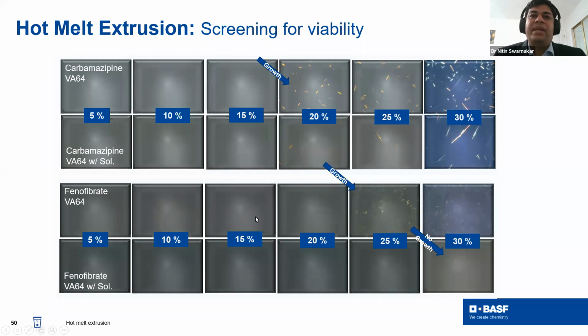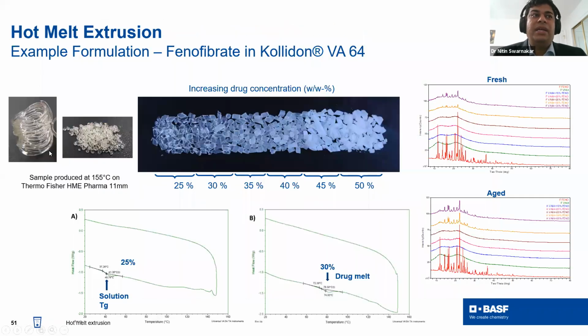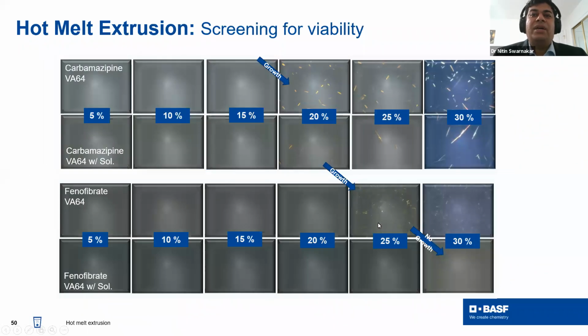But in the case of fenofibrate, without solubilizer, you can see crystal formation at 25%. But fenofibrate with solubilizer, which is Soluplus, you can see a much greater increase in the overall dissolution of fenofibrate. So this experiment you can do in your lab. It's very easy to do, and you can establish the ratio which is going to work. And this is very much translated into the real world. You can see here, we found that 25% is going to work.